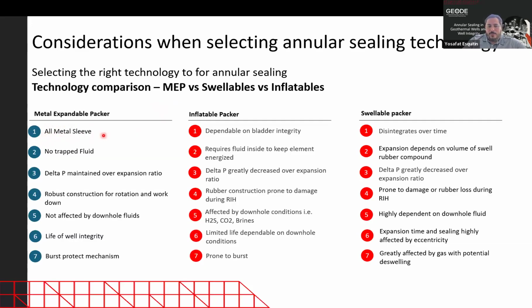So an all metal sleeve will always be more reliable for life of well sealing than elastomeric components like the bladder or the swelling compound. Not trapping fluid, especially on those geothermal wells, is very critical, because this fluid trapped in those chambers of the packer will have very high delta T's across the life cycle when you're cooling the well and heating it back up. As you heat it up, you're going to increase the pressure inside that packer and potentially burst it. So making sure that you don't have trapped fluids is very important.